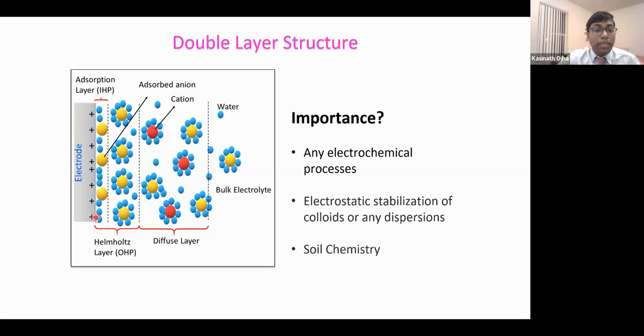This initial solvent layer we call the inner Helmholtz layer. And sometimes, depending on the ions or species in the electrolyte, they can specifically adsorb on the electrode. Particularly anions bind chemically with the electrode. Those layerings are called a double layer because we have two layer formations. One is the Helmholtz layer: there is a solvent layer, the inner Helmholtz layer, and then there is an ion layer opposite to the charge of the electrode, and that ion layer we call the outer Helmholtz layer.